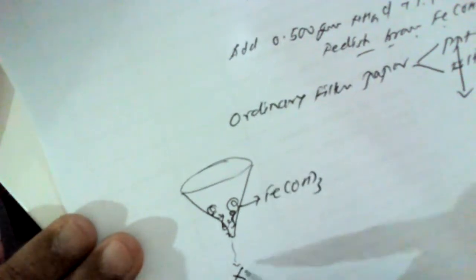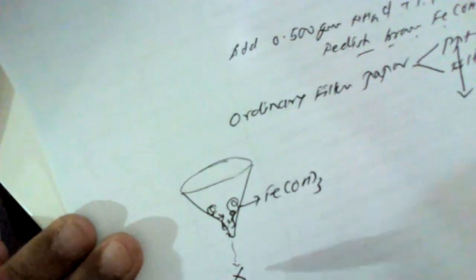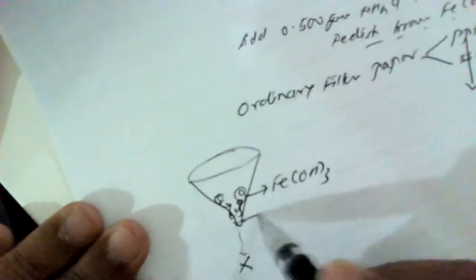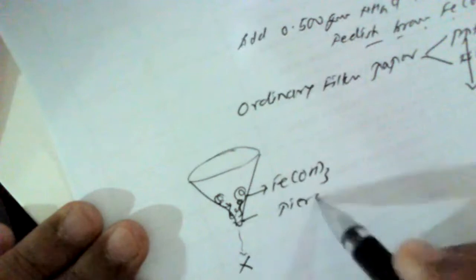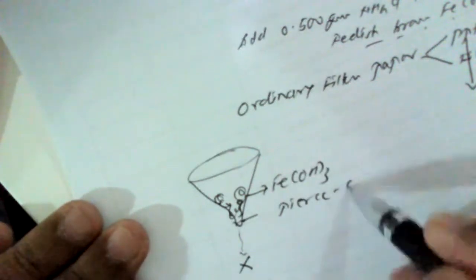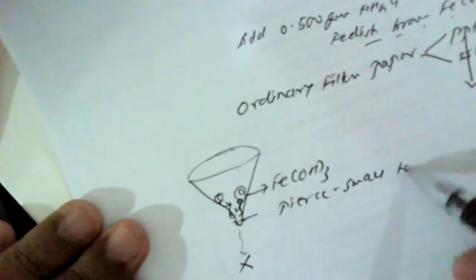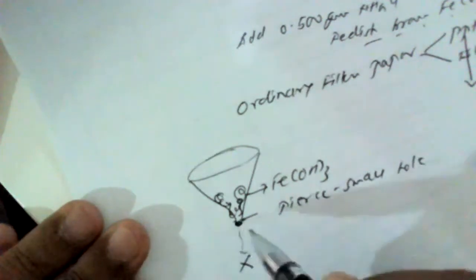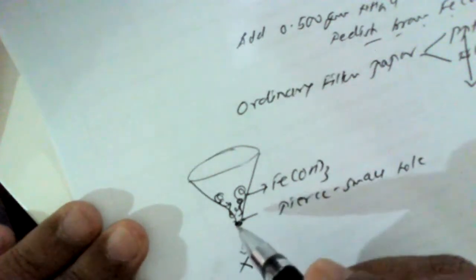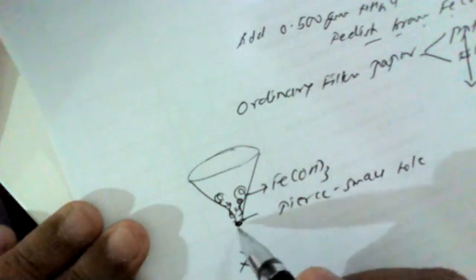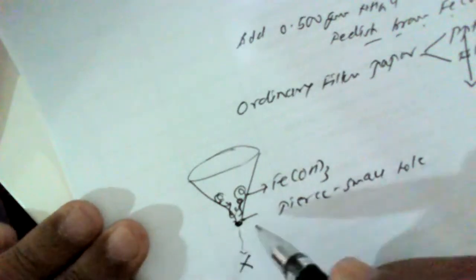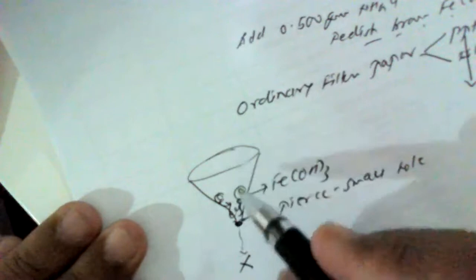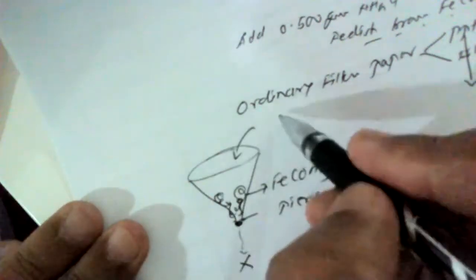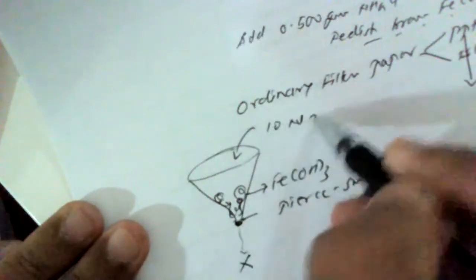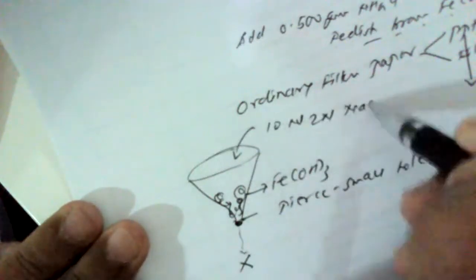After rejection of the filtrate, we have to pierce this filter paper. Pierce means we have to make a small hole at the bottom. That means here we have to tear this filter paper. Because the filter paper is moist, we can very easily tear it at the bottom. And now to this precipitate, we have to add again 10 ml of 2 normal NaOH solution.